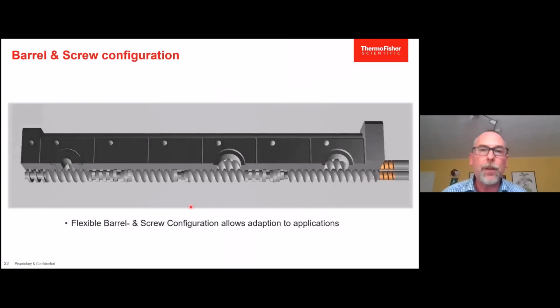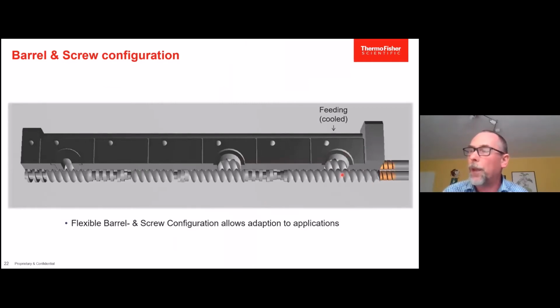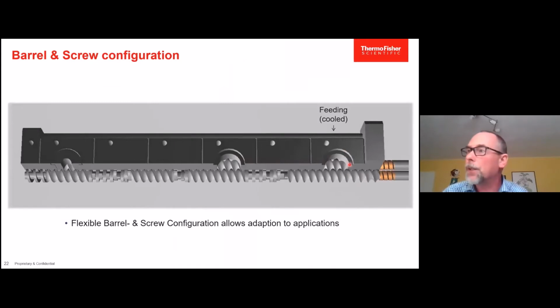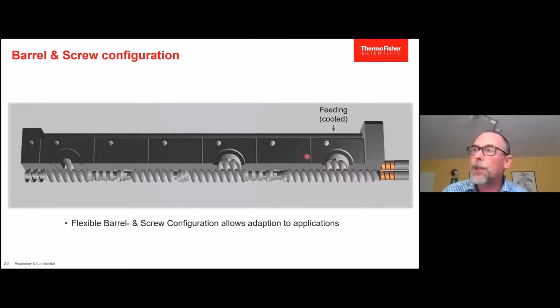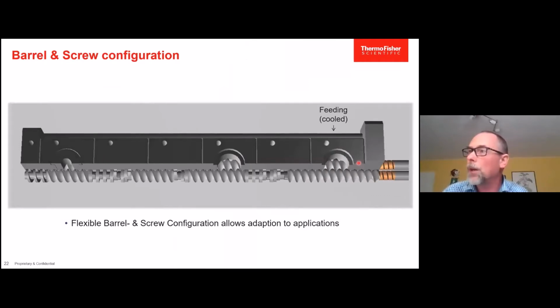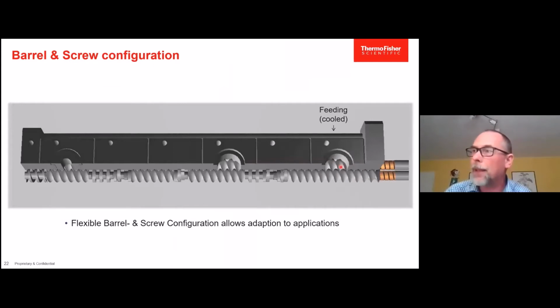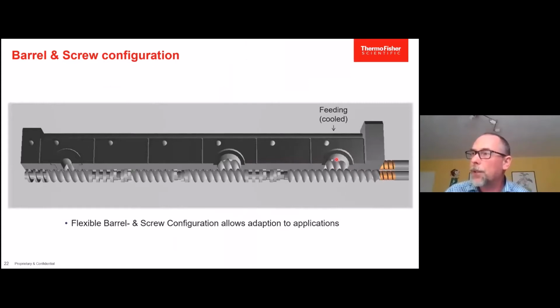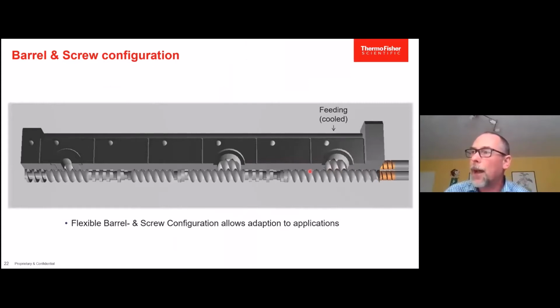And by arranging those screws, you see a typical screw configuration. When we start looking at the screw configuration in the first open port, we have the so-called feeding port. Usually it is cooled. The material will drop in. The extruder barrel usually is a hot process, so it's cooled to prevent the material melting in the feed section and to block the feed section. Once the material gets into the screws, it gets transported, heats up, and when it arrives into the mixing zone, the pellets are crushed, molten, and pushed over to the next conveying zone.